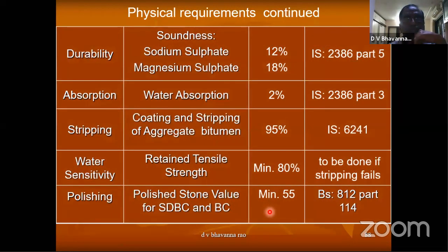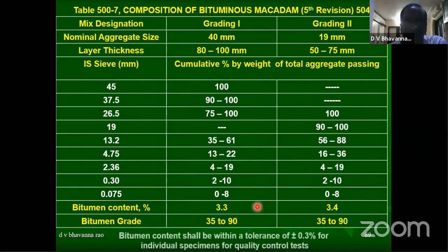Also, durability test and water absorption test, stripping value, minimum 95%. Retained tensile strength shall be minimum 80%. Polished stone value is required for wearing coats, minimum 55%. This is gradation for BM.